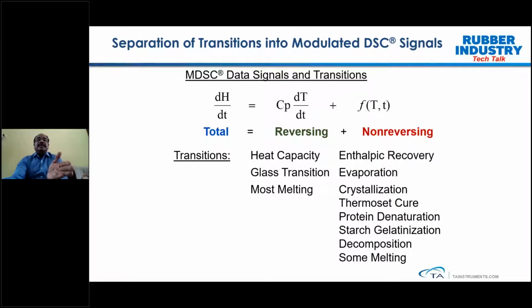The MTDSC can give you three signals in total, which carry all the transitions. The reversible heat flow shows only the heat flow related to heat capacity, and the non-reversible heat flow takes all the transitions which are due to kinetics, could be evaporation, crystallization, curing, all that sort of transition.